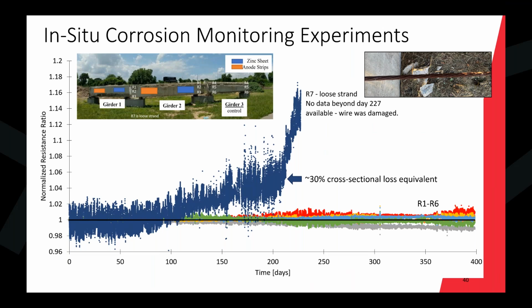So you're seeing within about 200 days, we're up to a loss that in the mechanical tests would equate to about a 30% cross-sectional loss. So it's beginning to come apart. And then from that point, it rapidly accelerated. And unfortunately, somebody in maintenance accidentally cut one of the wires out in the field here. So we lost the data before it completely disconnected. That would head up to infinity at that moment.